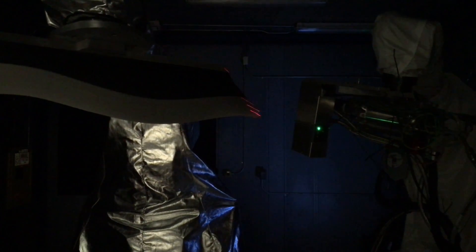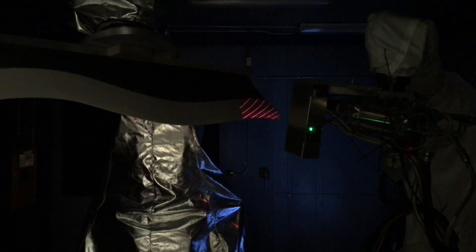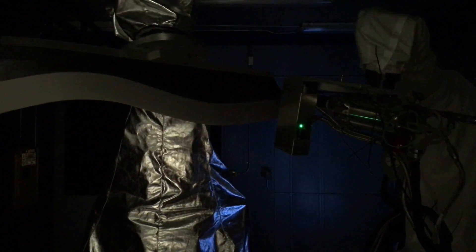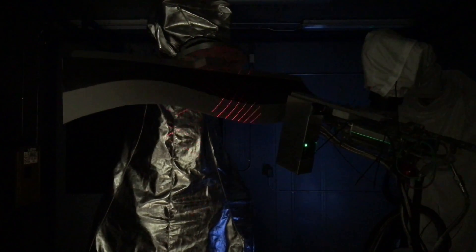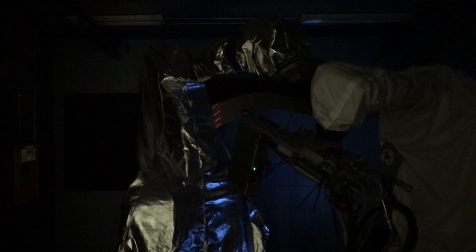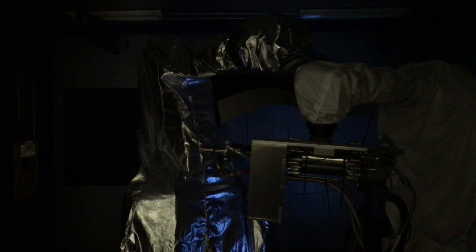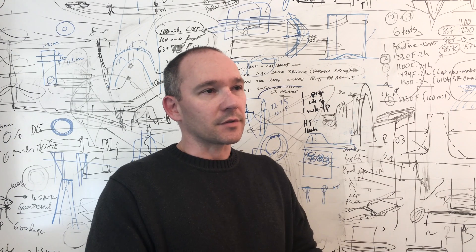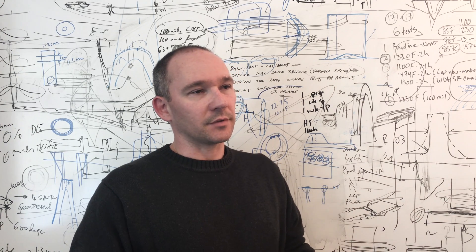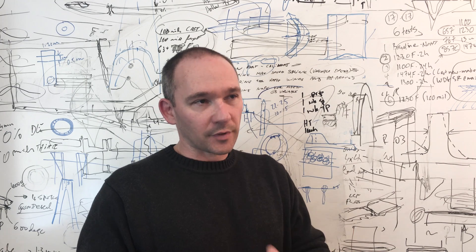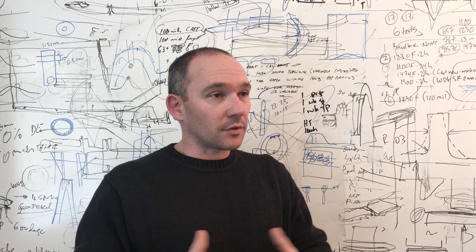Since we are working in a 3D environment that requires very complex toolpaths, we are using some machine learning techniques in order to not just strategize how you build the part, but also to modify the path in situ. And when we are measuring what we are depositing, we can correct if something doesn't go according to plan. That enables us not just to simplify the process, but get to a result in a much quicker time and reduce cost of the operation.